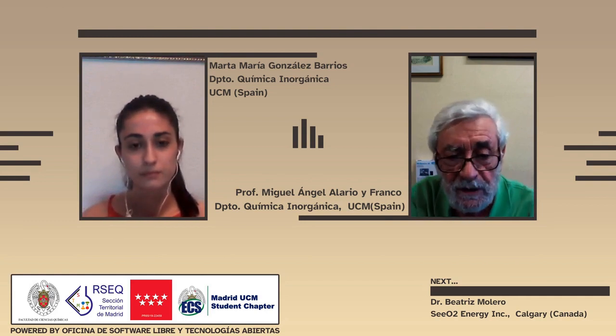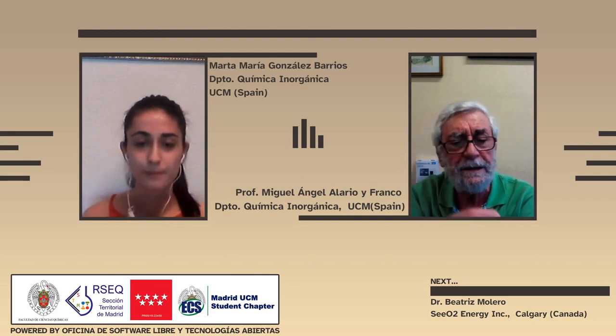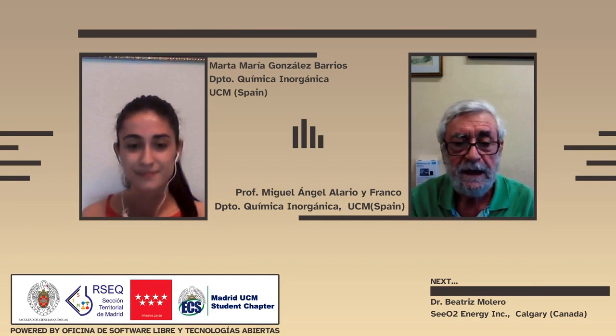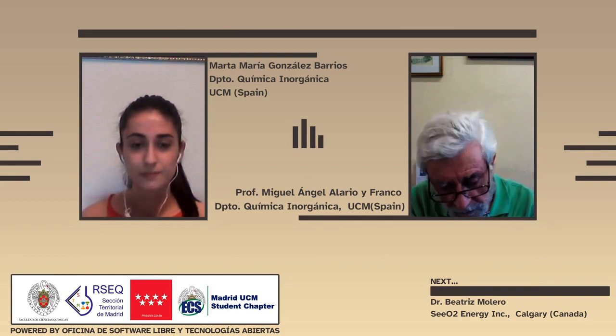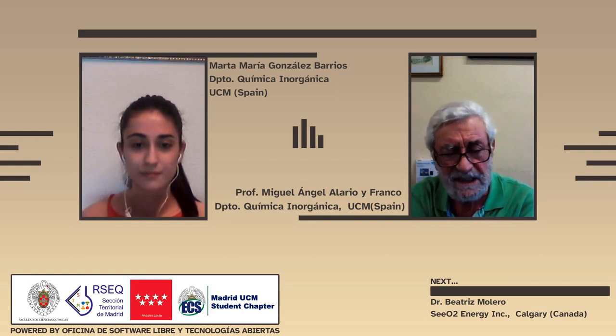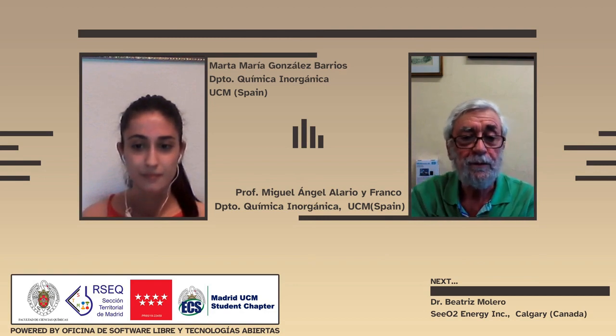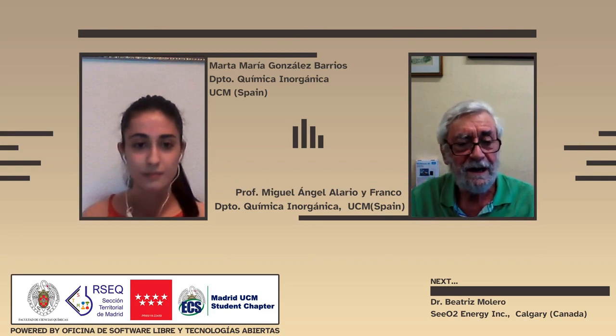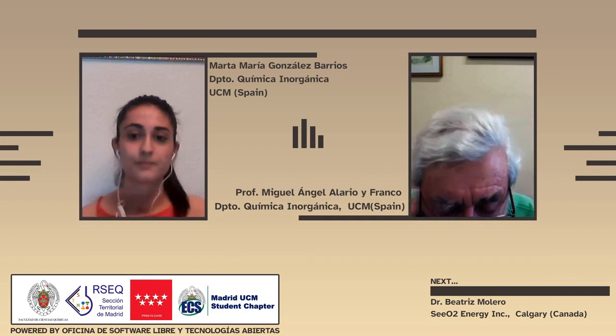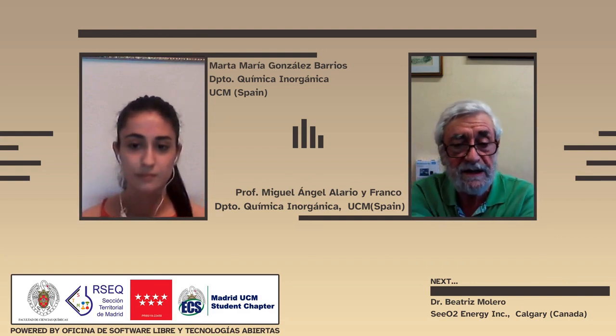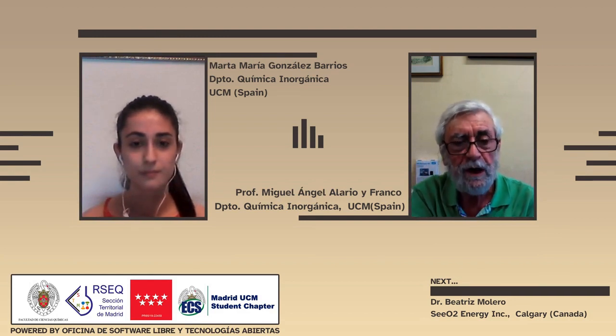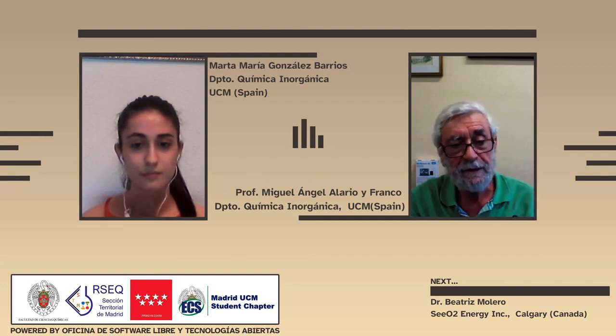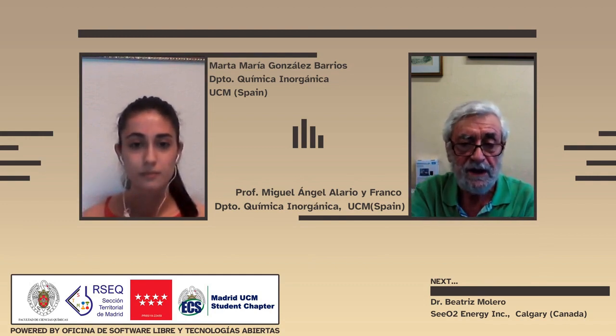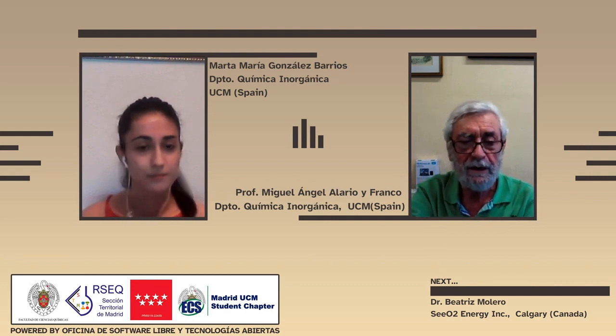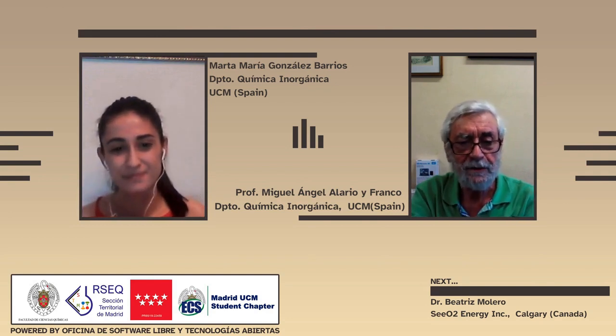So at the end, you can actually move two electrons. And this moving of the two electrons is actually a quantum phenomenon. That's a little more complicated to discuss, but the idea is that when you put two electrons, they become a quantum state in which they don't have resistivity. From this on, things become much more complicated. I showed you a formula in which a very important point was the Debye frequency. The Debye frequency is a particular characteristic vibration frequency of the lattice. That means that depending on the lattice, the frequency is higher or smaller, and the Tc, which is directly proportional to the Debye frequency, can change. But I wouldn't go further because I don't know much more, and it is a little complicated for just a general talk.